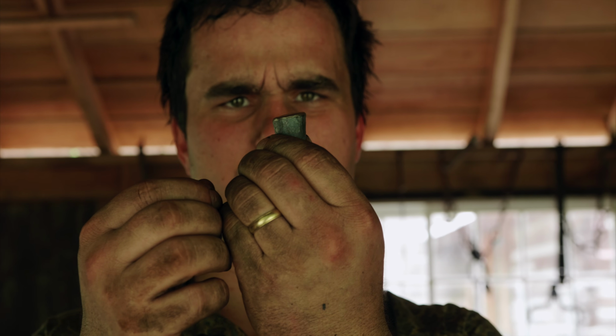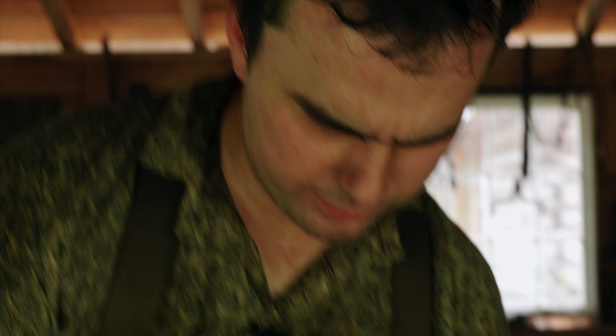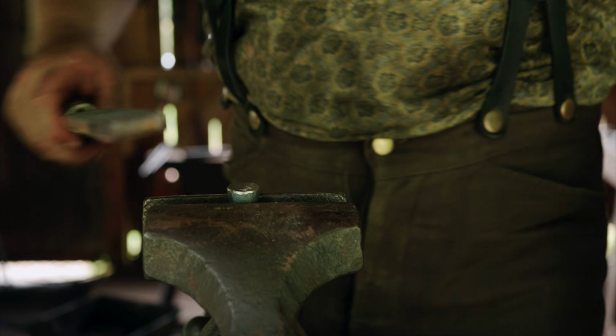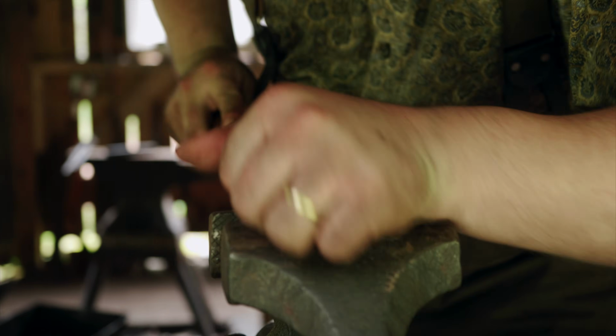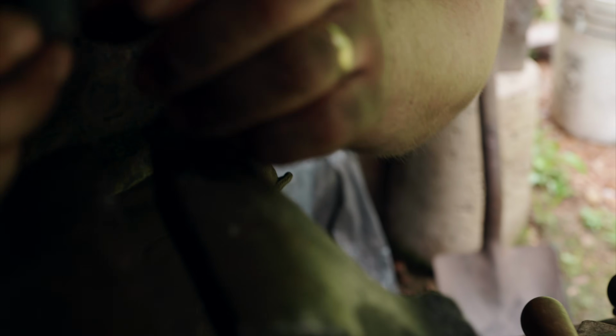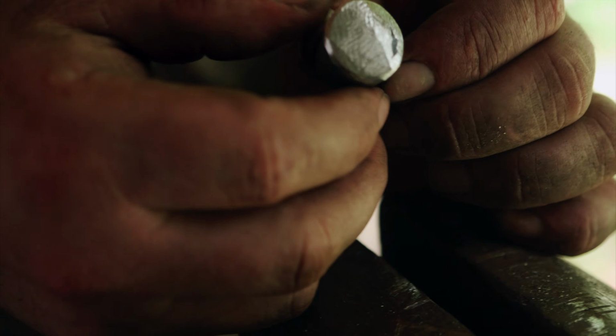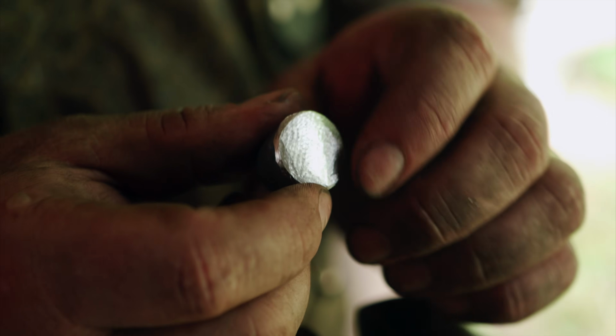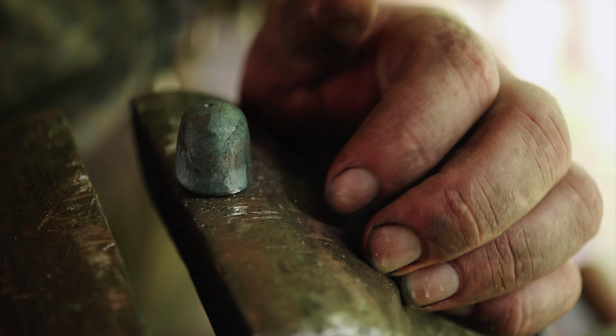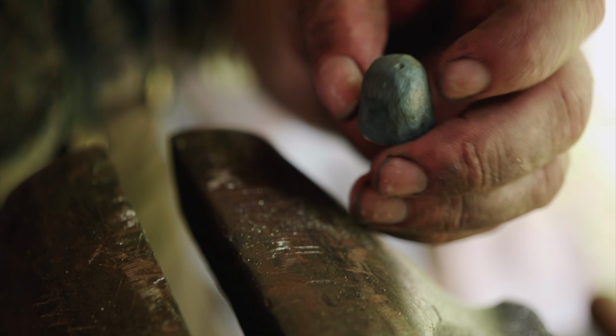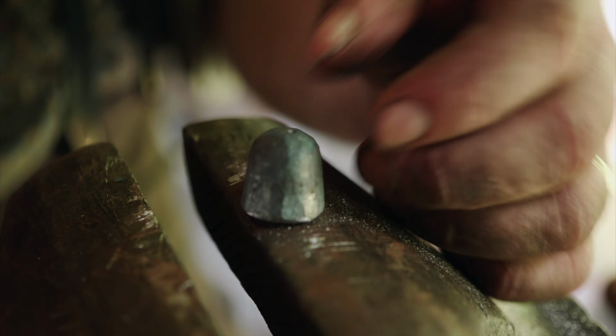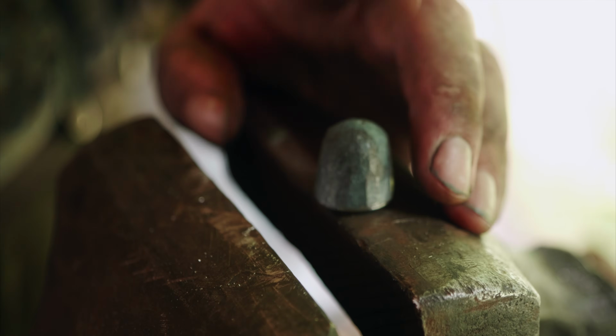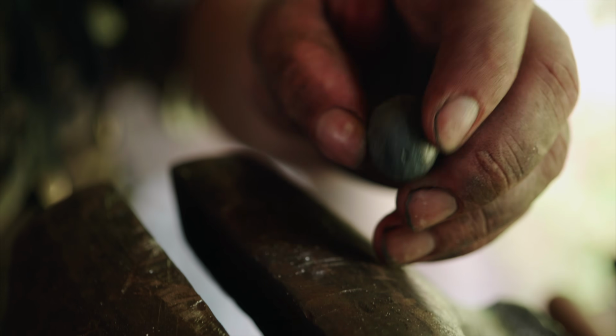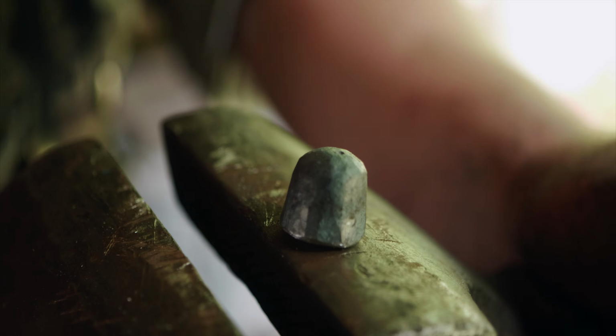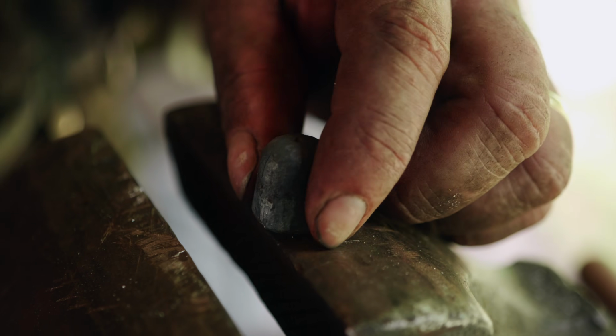It's still really bad. I think we can use that. So the base is not quite flat. It's actually rounded a little bit. It's also important when filing a piece of high carbon steel to make sure that it's not too hard before you file, or you'll trash your file. I did that by letting this air cool instead of quenching it off, because if I'd quenched it off in water, it would have gotten hard.